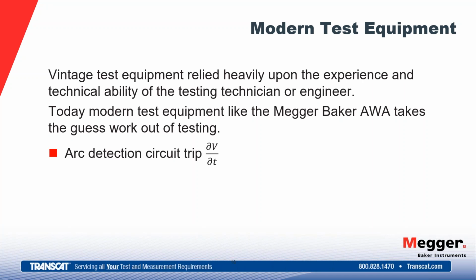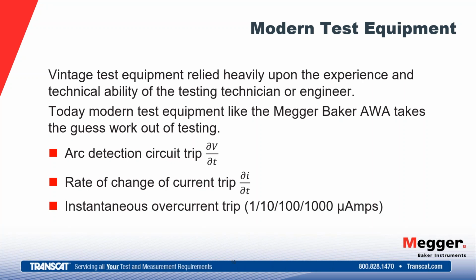So it has an arc detection circuit, which basically looks at the change in voltage over the change in time. If it detects that arc, it's going to stop the test. It's not going to continue to dump that energy into that fault. So arc detection also uses the rate of change of current. Again, the hardware is watching current. If the current rapidly increases, it's going to trip the tester and stop the test and not continue to dump energy into that carbonizing type of fault.